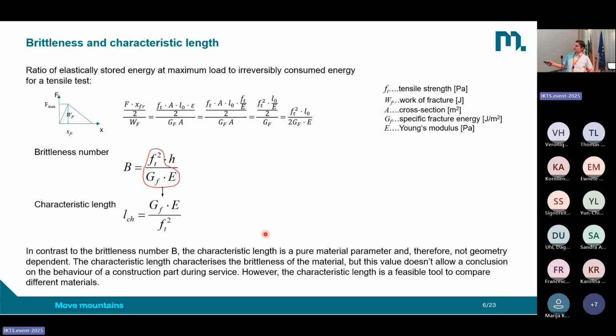Then we can use the strength of the material, multiplied with the cross-section of the crack, to replace the force. And then we can replace this displacement by the length of the sample times the strain at maximum force. And we can replace the work of fracture by the specific fracture energy multiplied by A. Specific fracture energy is the energy per unit area which is consumed. And in the end, we get a relation which is the squared tensile strength multiplied by the length of the sample, in this case the length of the tensile test, divided by the specific fracture energy multiplied with the Young's modulus. And this is, so to say, the balance between elastically stored energy and work of fracture for a tensile test, describing then the brittleness of this tensile test.